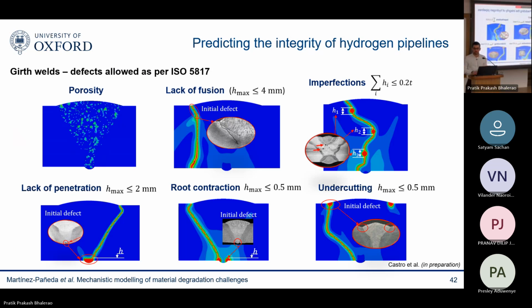Out of the welding process, you have a lot of defects in place, so you can put those defects into your model, and you can see how hydrogen will lower the pipeline's tolerance to them. Standards will let you do welds and get away with certain types of defects. Whether those defects are going to be problematic when you bring hydrogen or not, that's the good question, and a question that you can answer with the model, and that is very difficult to answer with experiments.